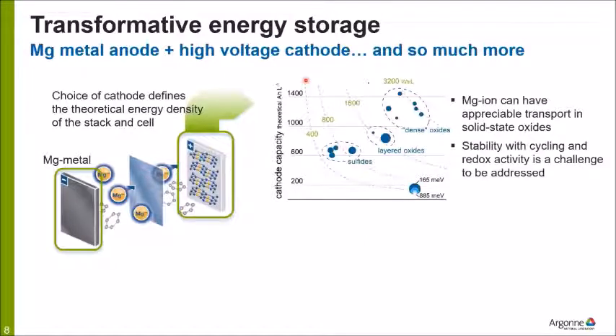I showed this plot several times, so many of you may have already seen it, but this is the charge capacity, and this is voltage. Sorry, I don't know why I got cut off there. Of different cathode insertion voltages for different cathodes. The size of the points you see here are proportional to the calculated nudged elastic band calculations of mobility for magnesium. So the larger, the higher the mobility would be expected. So you can see once again, we obviously want to get up to the dense oxide materials to get to the higher energy densities as given by these isoenergetic lines.